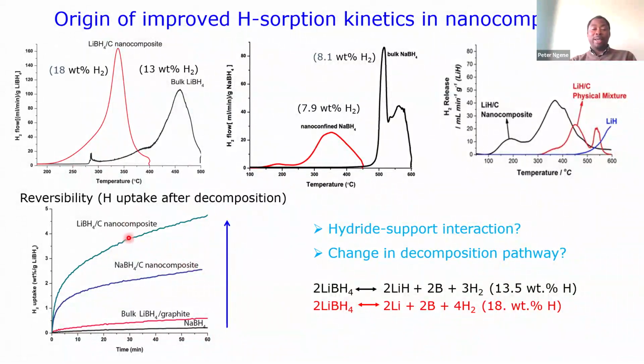Another thing I did not show here, because it would be too much, is that with this same sample we can play a trick, and we did it in some of the publications. We can add a catalyst in here, something like nickel. A very small amount of it, even 1 weight percent; you put the catalyst inside the pores, very close to the compound. And what happens is that you can really increase the rate of this hydrogen uptake even by half.